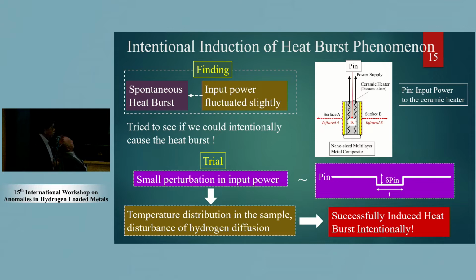If we investigate this spontaneous heat burst phenomenon in detail, we found that the spontaneous heat burst was induced maybe by the input power fluctuating slightly. So we intentionally give a fluctuation, a perturbation of power input. So this is the power input fluctuation. And if we give the power input perturbation, a temperature distribution in the sample and a disturbance of hydrogen diffusion would occur. And we finally successfully induced the heat burst intentionally.